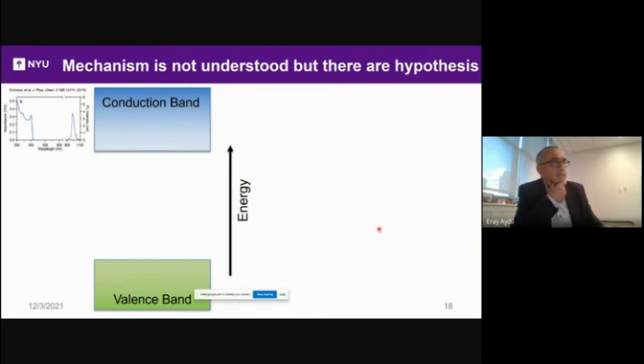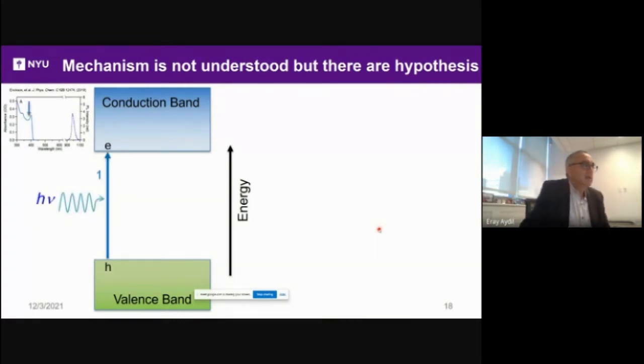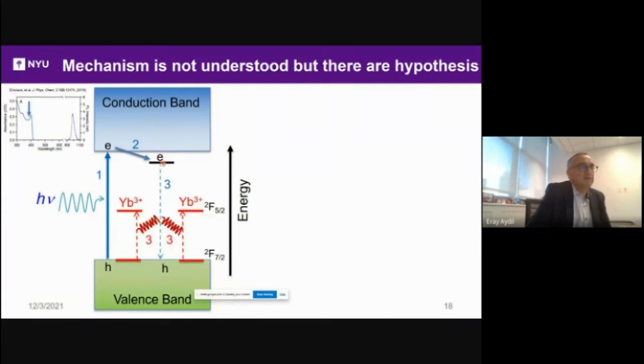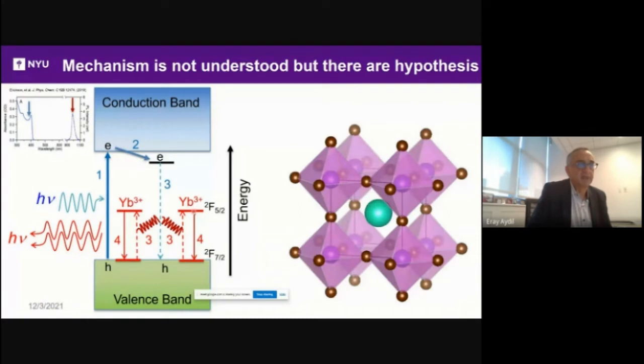Another one invokes a blue photon getting absorbed and then trapped into a defect, and then that getting coupled into 2 ytterbium 3+, and then near infrared photons being emitted from the ytterbium 3+. This energy is very close to the silicon band edge. So ytterbium is nearly perfectly matched to the silicon band edge.